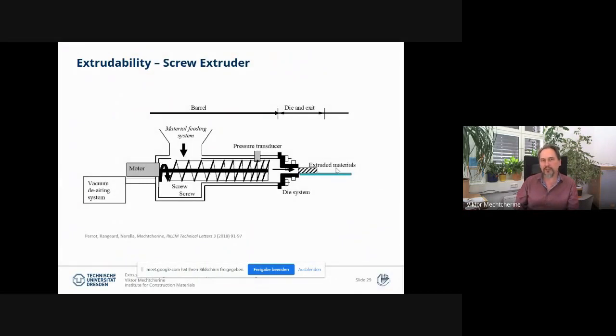What is very effectively used is a screw extruder, which looks like shown here in this sketch. We have here quite stable flow, but it's not easy to describe the exact quantity delivered per unit because we have also here some backflow. And again, depending on the consistency of concrete, on the rheological properties of concrete, that backflow can be more or less pronounced. So for usual screws, it's a really difficult task to predict even the quantity we deliver for a particular, let us say, number of rotations per time unit.